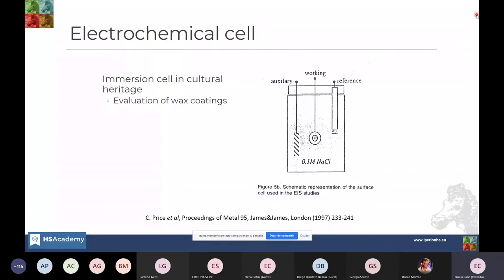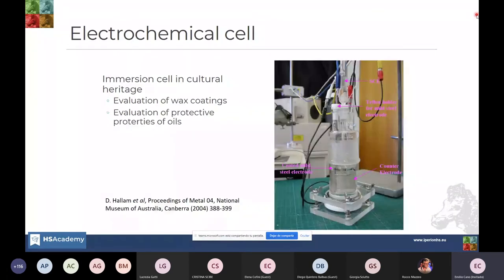And the same group, David Hallam and co-workers, presented much later another similar study, in this case studying the protective properties of lubricant oils for iron and steel. And you can see this is the same scheme. This is a V-cell, with a slightly different arrangement of the electrodes, but again the three electrodes: the working electrode, the coated steel electrode, a counter electrode, which is this platinum mesh, and here you see the saturated calomel electrode, which is the reference electrode. But you can see that this device can be helpful for some studies, but you have to immerse the sample you want to measure, which is not very convenient in all cases.